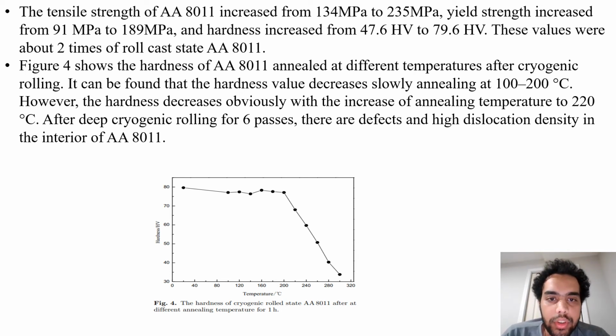Figure 4 shows the hardness of aluminum annealed at different temperatures after cryogenic rolling. It can be found that the hardness decreases only slowly when annealing at 100 to 200 degrees Celsius. However, the hardness decreases obviously with the increase of annealing temperature to 220 degrees Celsius. After deep cryogenic rolling for 6 passes, there are defects and high dislocation density in the interior of aluminum.